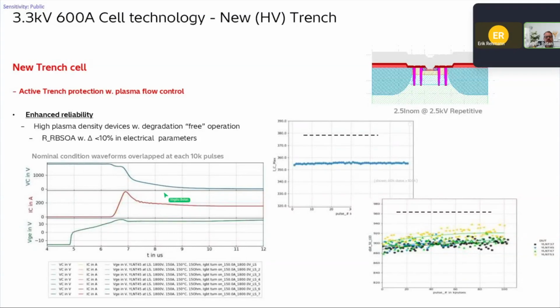what we do is we intentionally go into dynamic avalanche. So we run pulses, turn-on, turn-off pulses at SOA conditions: 2.5 times the nominal current at 2.5 kilovolt for a 3.3 kilovolt device. And then under these SOA conditions we apply 100,000 pulses, and we look at the turn-on event and waveforms and the difference in di/dt and dv/dt.